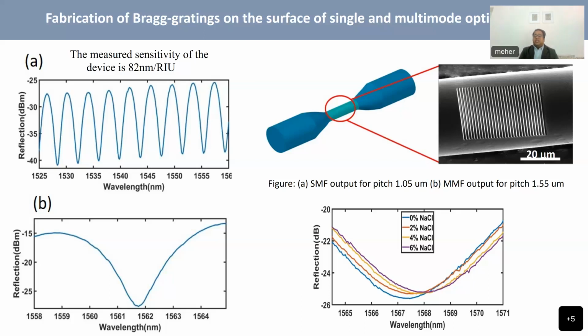But in the case of photonic sensors, we cannot coat conductive material on the surfaces very often. So we wanted to make the patterns without coating the conducting material. And the process was optimized, and it took me around 3 to 4 months to optimize the process. But we got very nice results.